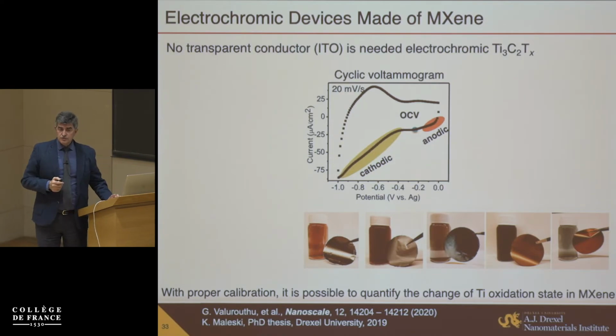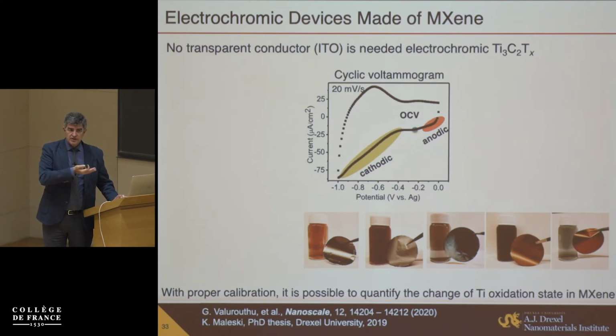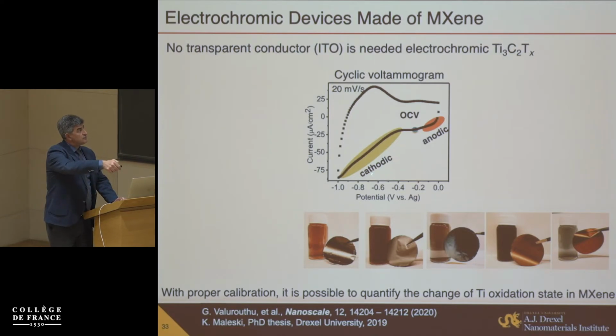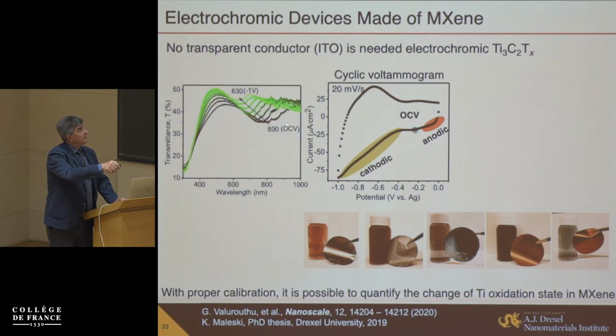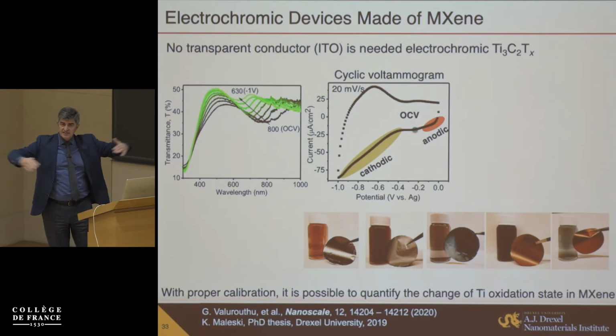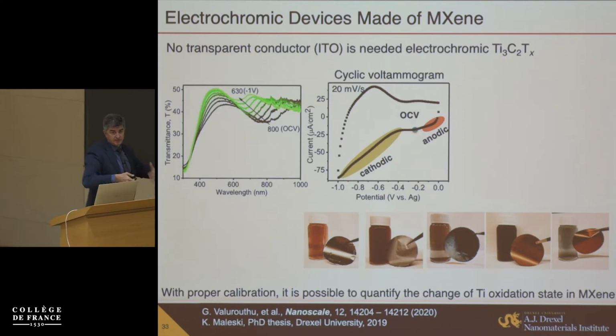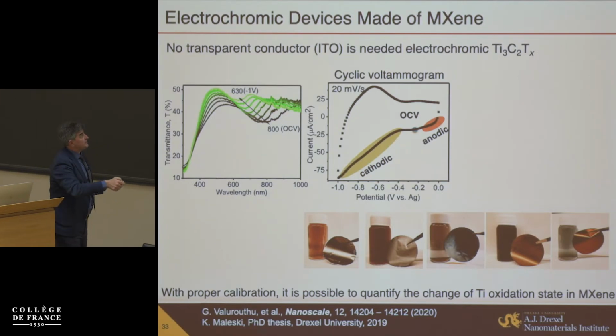And I mentioned to you that by changing the oxidation state of MXene, we can basically monitor the oxidation state of the transition metal, because this transverse surface plasmon only depends on oxidation state. So flake size, lateral flake size doesn't matter, spacing between flakes doesn't matter here. It's primarily the oxidation state. So what happens?